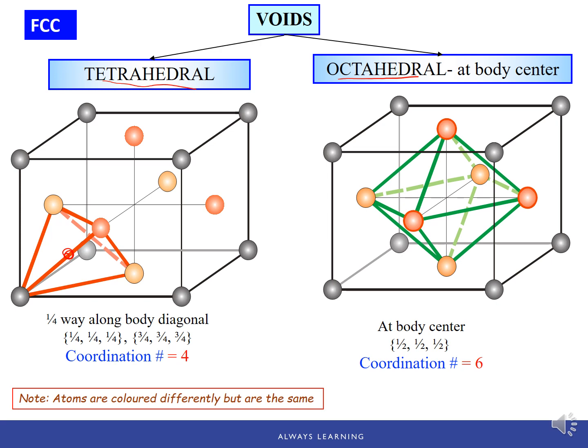So this tetrahedral interstitial site is formed by 1 corner atom, in the gray color, and 3 adjacent face center atoms. And the 4 atoms are close touched, close packed, and in the middle there is a void. So that's where another cation or another oppositely charged ion can be placed. So that's the tetrahedral. The octahedral, which has a coordination number of 6, is formed by the 6 face center atoms, and the oppositely charged ion, for example a cation, can be located in the middle of this interstitial site to form the ionic bonding.